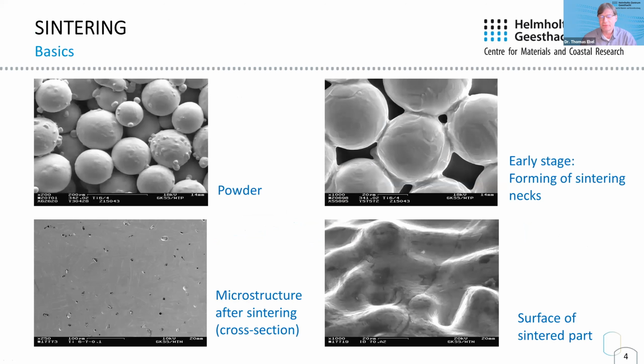Sintering itself is in principle a very simple process. So you have the powder, you heat it up, and you will observe that in the early stages, sintering necks are formed, and these necks grow. And after a while, usually several hours, you get a nearly dense material. You have some small isolated pores, but the rest is a homogeneous material, and you cannot recognize the original powder particles. So it's a new material, so to say. That sounds simple, but the problem is always, in the case of metals at least,